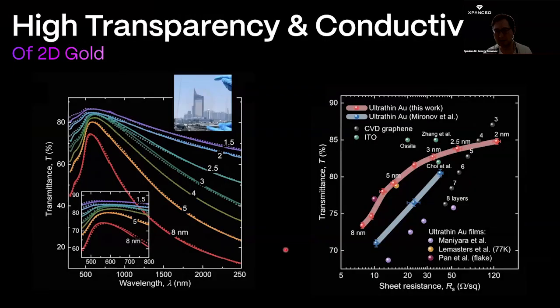And because of that, and other effects, and because it's very close to the bulk properties, we observe that our films demonstrate really nice conductivity. So it's really small resistance. We can see its sheet resistance is comparable to indium tin oxide, and even outperforms the famous CVD graphene sheet resistance, and has one of the best trade-offs between the transmittance and sheet resistance.